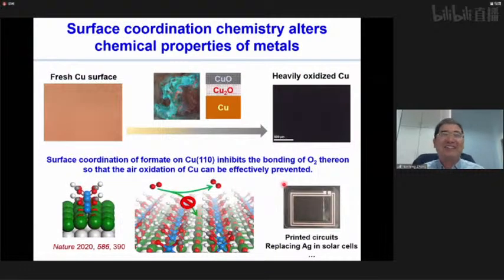For example, we all know that copper is really easy to oxidize in air, because copper oxide and cuprous oxide are not dense structures. So they cannot form condensed passivation layers on copper. So when we expose copper to air, it will continuously oxidize until we get a highly oxidized copper surface, which is covered by copper oxide.